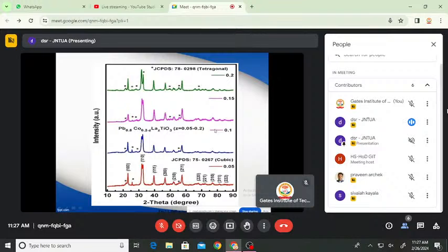Coming to the XRD analysis, the XRD patterns are shown here. From the XRD pattern, it is clear that the prepared nanoparticles, here we are changing the lanthanum composition. Earlier we changed the cobalt composition, now we are going to change the lanthanum composition from 0.05 to 0.2 with respect to alteration of cobalt composition. It has revealed the formation of a few tetragonal phases of PT structure. These tetragonal and cubic phases are found to be compatible with the standard JCPDS files, as I have represented here with the file number. The cubic reflection planes were represented in the X-ray diffraction pattern. It is clear that there was an absolute transformation of the unit cell from tetragonal to cubic structure.